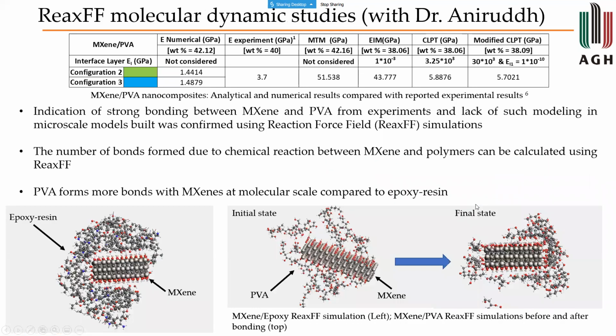But for a polyvinyl alcohol polymer, the experimental results were almost twice or more than twice compared to our numerical models. So the root cause of such problems is that when we model nanomaterials with composites, with polymer, a chemical bonding takes place.